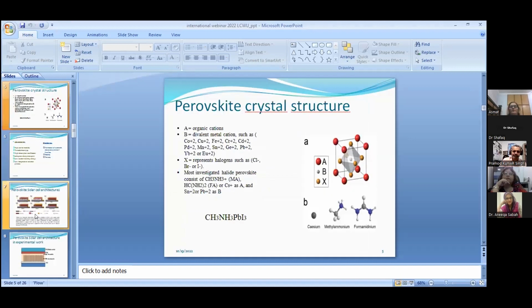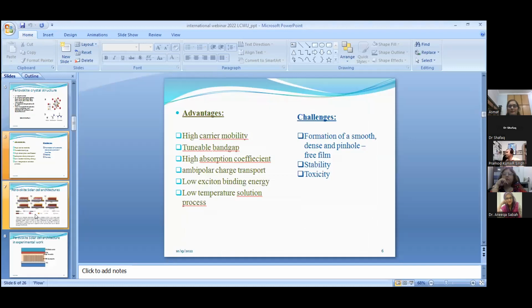Okay, now continue with these advantages and the challenges with the perovskite. So perovskite has a lot of advantages: it has high carrier mobility, we can tune the band gap, it has a high absorption coefficient, it has high ambipolar charge transport, it has low exciton binding energy, and we can prepare the perovskite solution at low temperature in our labs. Although perovskite has a lot of advantages, in the fabrication of perovskite solar cells we face a lot of challenges. First is the formation of a smooth, dense and pinhole-free film. It is a great challenge for the fabrication of the perovskite solar cell. The second one is the stability, and because lead gives high efficiency, the toxicity of the lead is also a big challenge in perovskite solar cells.